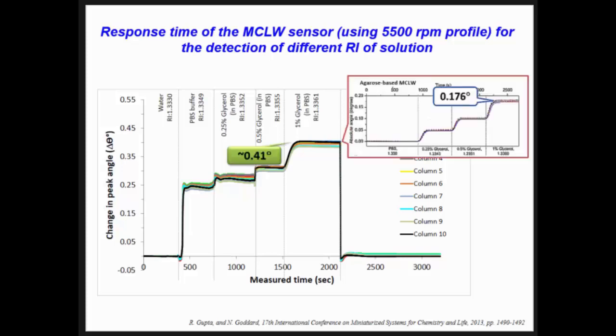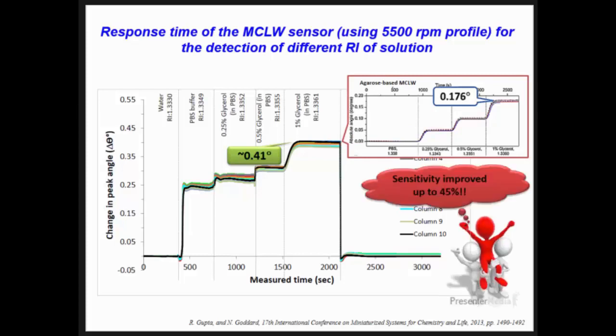The interesting part of this is, when we compare our system with the previously reported agarose-based metal clad leaky waveguide sensor, our improvement is about 45% from the previous one. This is due to the porosity of the acrylate-based hydrogel, as well as the functional group from NHS that covalently bonds with the NH group from the acrylate. Therefore, it gives very high sensitivity on the device.